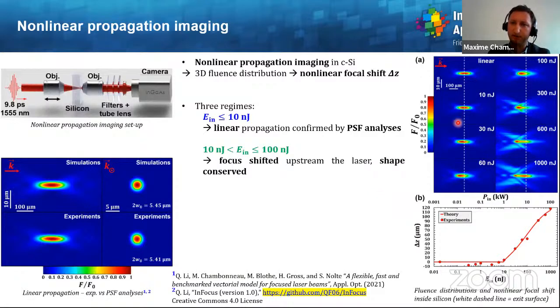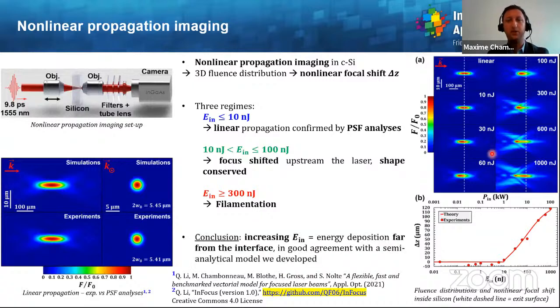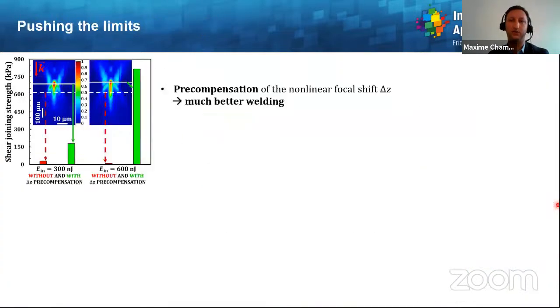Then for intermediate pulse energy, up to 100 nanojoules, we can see that the focus is unambiguously shifted from the initial position in the linear configuration. However, the shape is conserved in this case. And the last regime, for more than 300 nanojoules, is the filamentation regime. And here you can clearly see it with the focusing and defocusing dynamics. So the conclusion of this is that increasing the input pulse energy will lead to an energy deposition far away from the interface, which is in good agreement with a semi-analytical model we have developed. You can check the corresponding papers I will give afterwards in the next few slides.